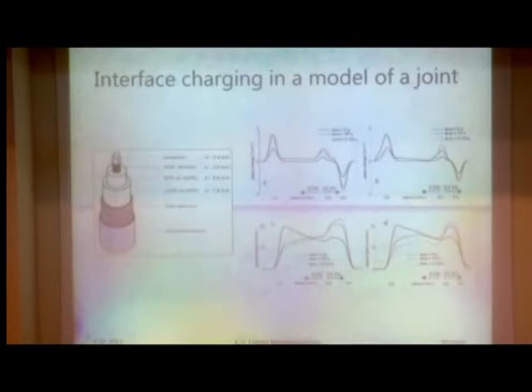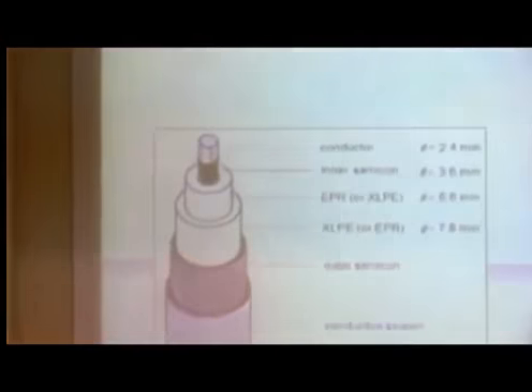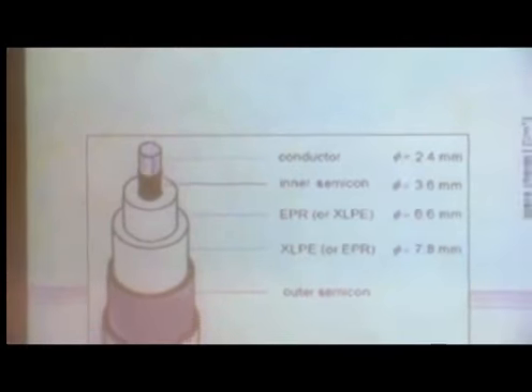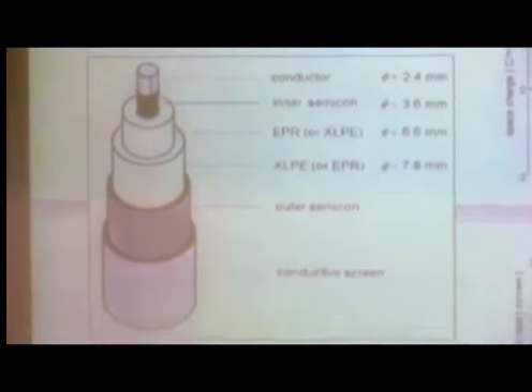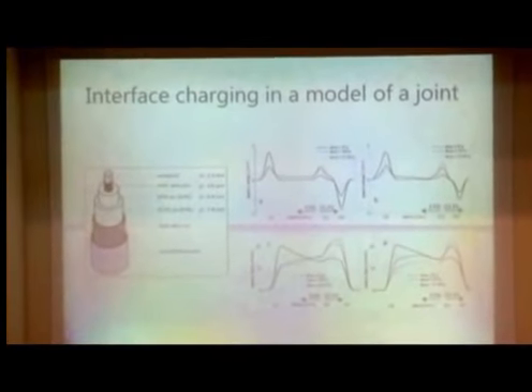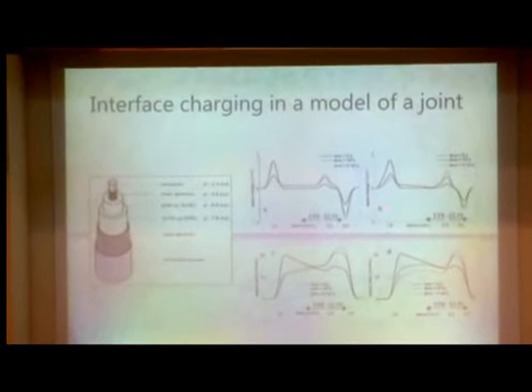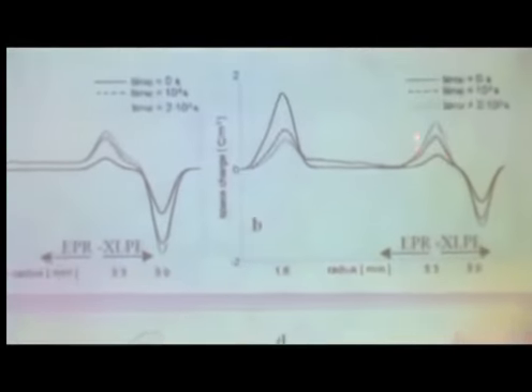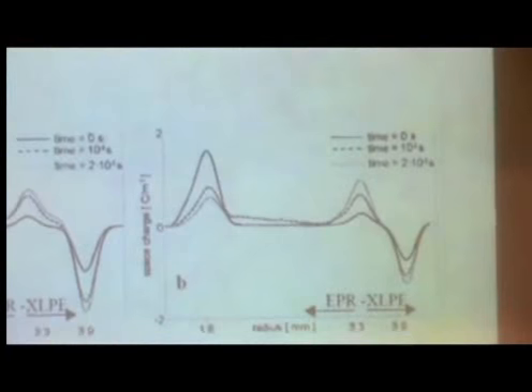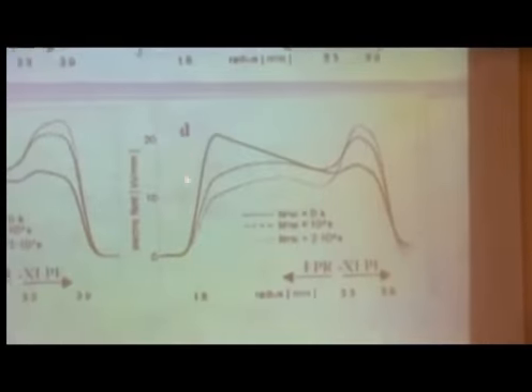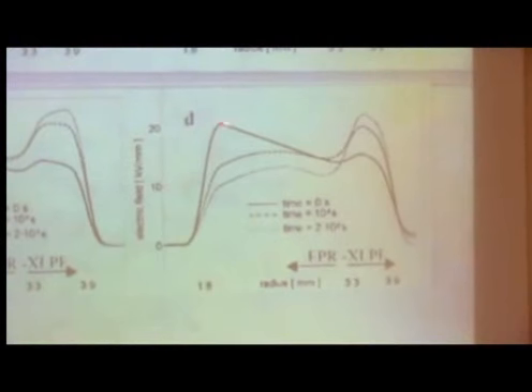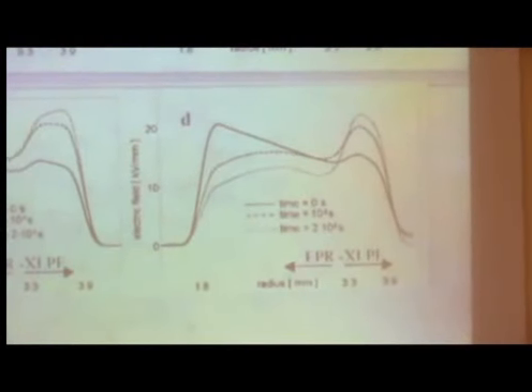Here are the results of simulations and experiments on a cable where we had two dielectrics, one EPR and one XLPE layer. It's a kind of model for an HVDC cable joint. If you put on a poling field and you wait for some time, you have to look at the right column here. This is the space charge distribution, which grows in time, as you can see here. And if you look at the corresponding electric field, you see that the maximum of the field moves from the inner conductor to the outer conductor. Okay, that's the measurement result.